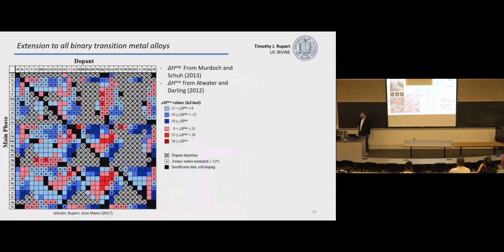Okay. But with that idea of segregation and negative enthalpy of mixing, we can go and make our own plot for what should work. So for example, we can go and make something that, if this is your base material, what would you want to add to create amorphous grain boundaries? Anything that's an X here means that it doesn't segregate. So it doesn't match that first criteria, that's not good. And then we want things that are blue, preferably dark blue here.